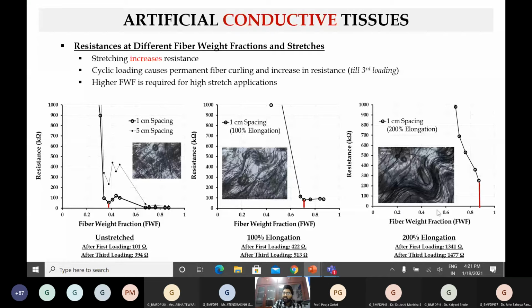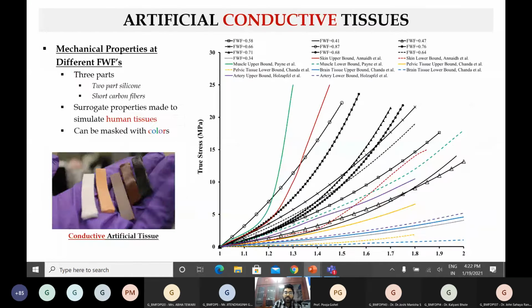Here we observe the fiber weight fraction needs to be super high, about above 0.8, which is not really desirable because the specimen gets really stiff and becomes fibrous. That is how much we need for a 200% elongation. So we concluded that for 100% elongation, it's manageable. But for an application requiring 200% elongation, let's say somebody is running and wearing a wearable device, that might not be a suitable device. So that is as far as the artificial conductive tissues are concerned in terms of electrical conductivity.